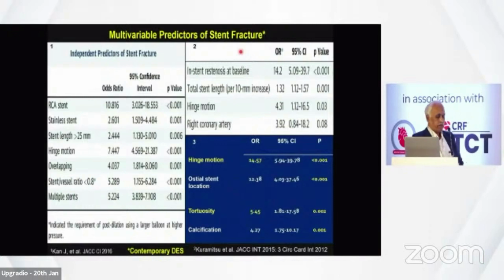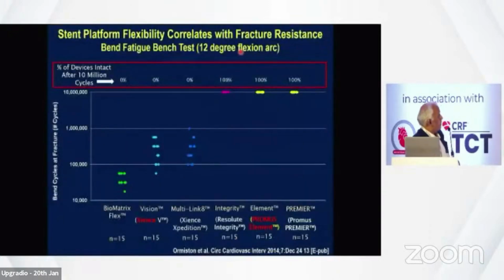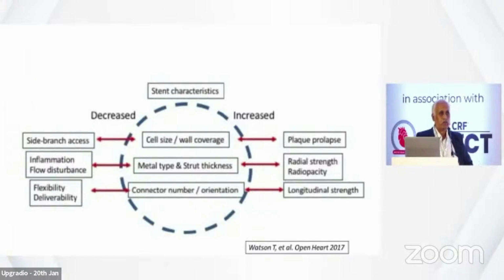And there are various problems, one of the important problems with the stent is the late stent fracture. What are the factors which are associated with the stent fracture? RCA stents, stainless steel, longer stents, hinge motion, overlapping, stent vessel angulation, multiple stents. So these are all various factors which influence the occurrence of stent fracture. In the bench testing, Integrity and Premier have, even at 10 million cycles, less strut fracture. This you can see in the graph here. So the late stent fracture is one important factor in the late stent thrombosis or restenosis. So it's always a trade-off. If you've got a thick strut, you get more radial strength.